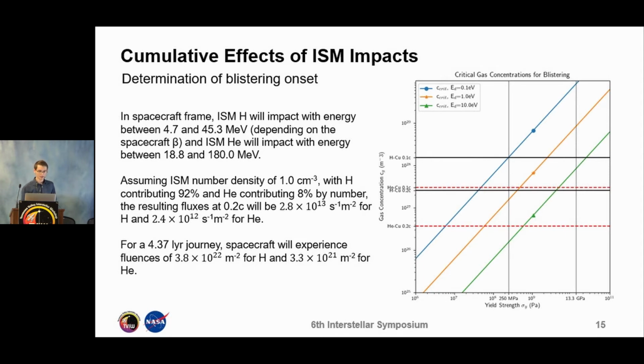Of course, this is a function of the travel speed, whereas the fluence, the total integrated impacts, is independent of the travel speed. And for a 4.37 light-year journey, which is approximately the distance to Alpha Centauri, we expect to see fluences of order 3.8 times 10 to the 22 per meter squared for hydrogen and 3.3 times 10 to the 21 per meter squared for helium.